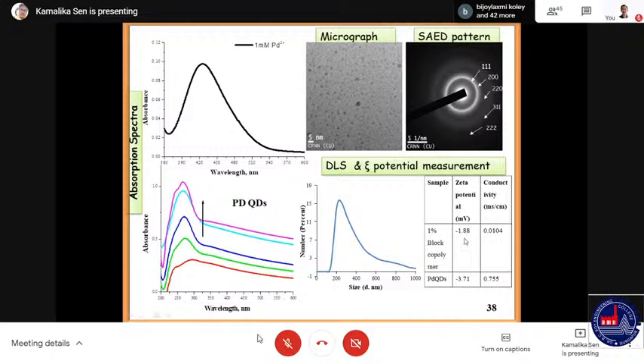And the zeta potential measurement, the electrical double layer measures the potential around the nanoparticles, which increases upon palladium quantum dot formation, which indicates the formation of nanoparticles. And if the zeta potential value increases either in the negative or in the positive direction, that means that the electrical double layer has formed, and that means your nanoparticle has formed in the solution, and that particle accumulates the electrical double layer on its boundary. The conductivity also increases as a result.